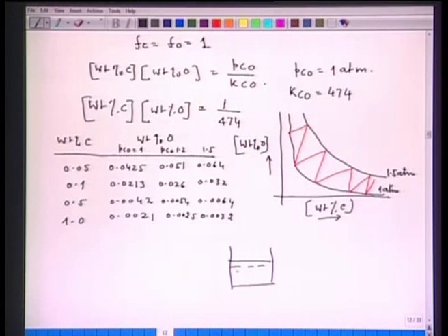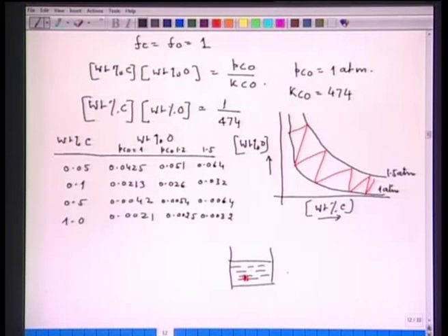This is hot metal, and from here, for example, a nucleation site is somewhere here, and a carbon monoxide bubble is evolved. So, at this particular location, if this is the nucleating site for nucleation of C plus O equal to CO bubble, then the total pressure on this bubble will be equal to P, that is P atmosphere plus this column pressure, rho L g H, where H is the bath height.